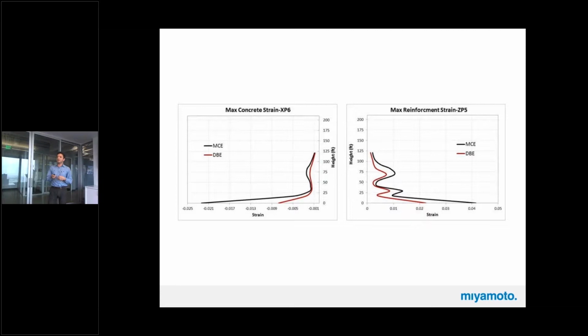And also we measured the strains in the concrete and reinforcing steel. This is one of the examples. We did that for all the shear walls and along the height, and also for all 7 time histories, and then we averaged them. We wanted to see where we passed the limit. The limit for concrete is 1%. And this is one of the cases where, in MCE level, the strain passes 1%, but in DBE level, we are fine as it was based on the code. But we want to improve the performance of this structure for extreme events, which is MCE level. So we identified the location of the concrete that basically has major damage, like crushing and spalling.